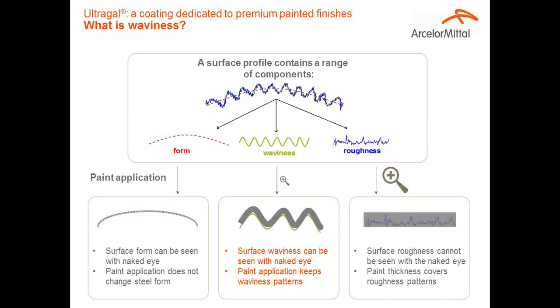We also have the roughness. The roughness is the micro asperities on the steel, the small peaks and holes that are at the surface of the steel, and that we cannot see by eye. Only with a microscope can we see them. And in between, there is in fact a pattern which is called waviness, and which concerns all the wavelengths between 1 and 10 millimeters. And this is a pattern which can be seen by eye, and which in fact determines the quality of the aspect of the finish after painting.